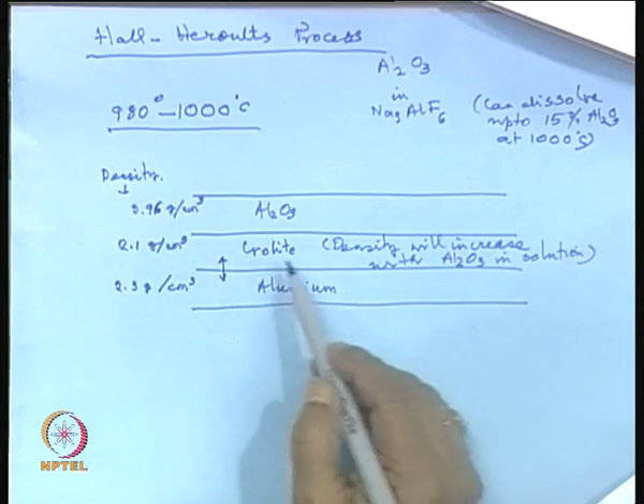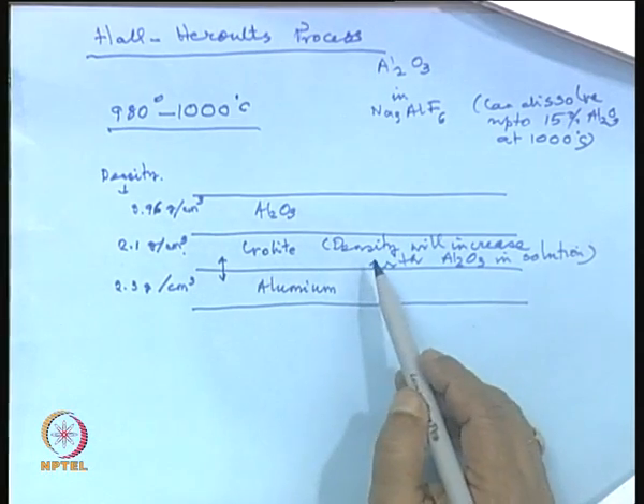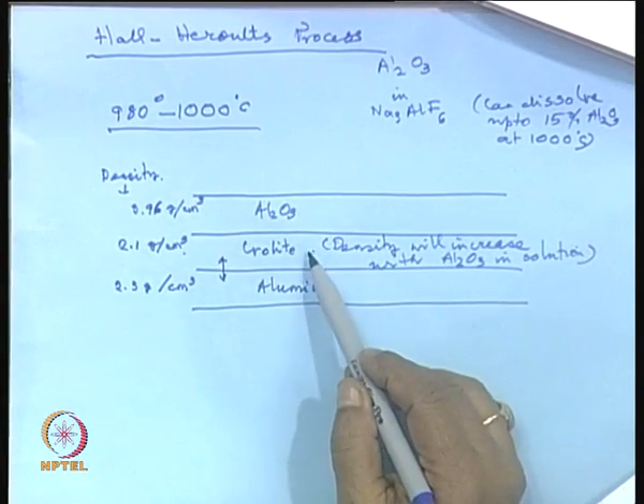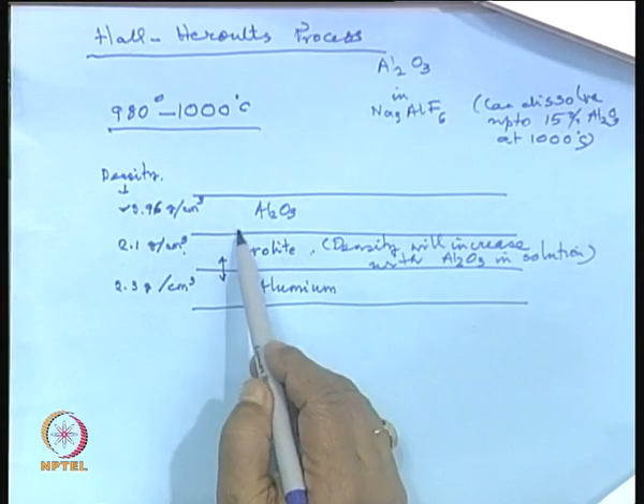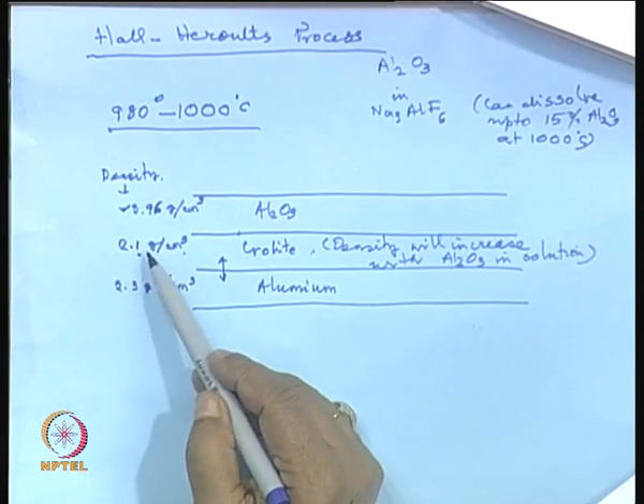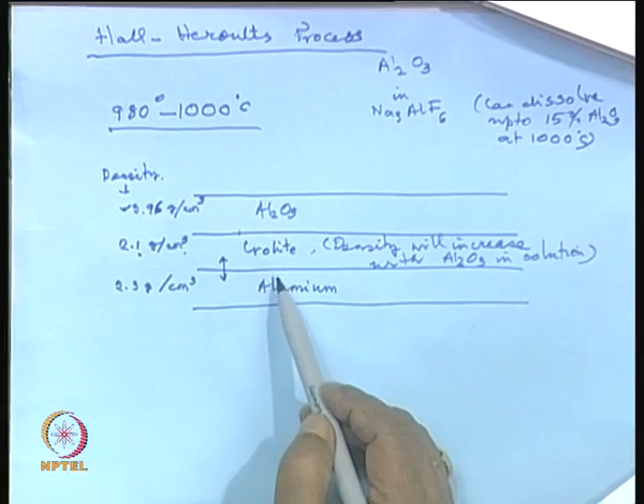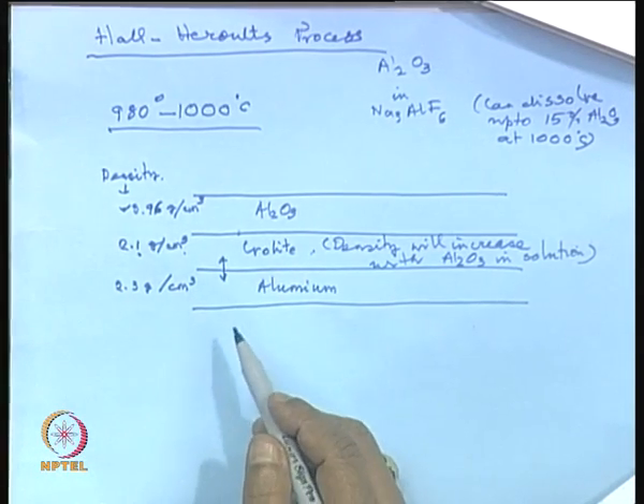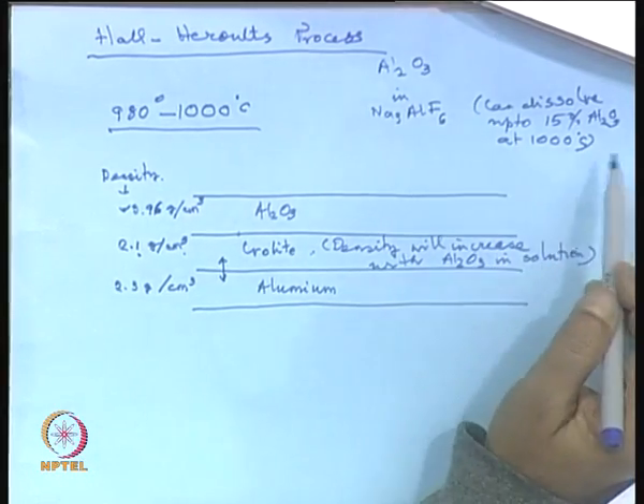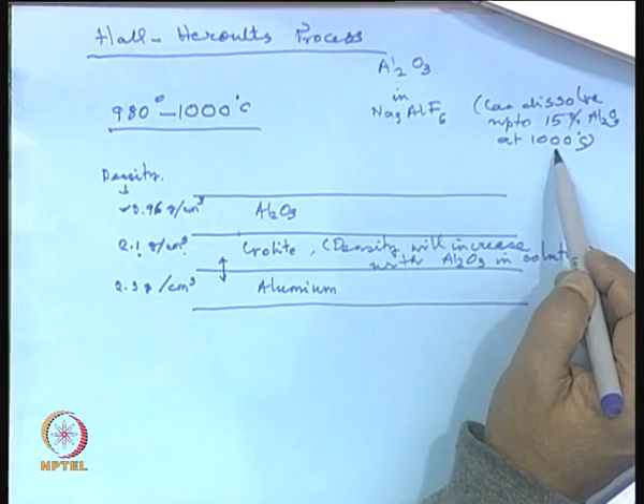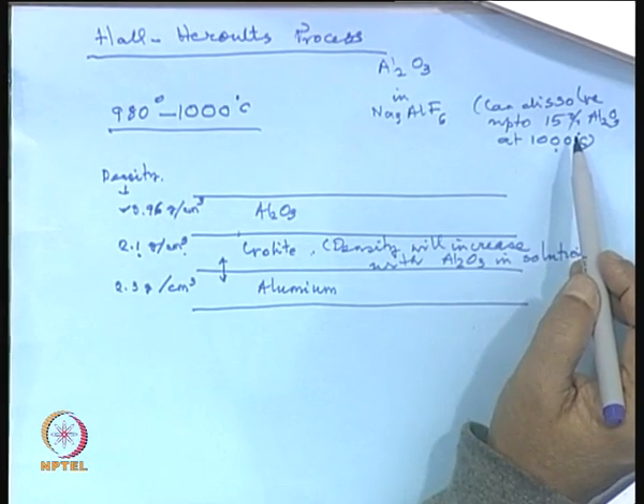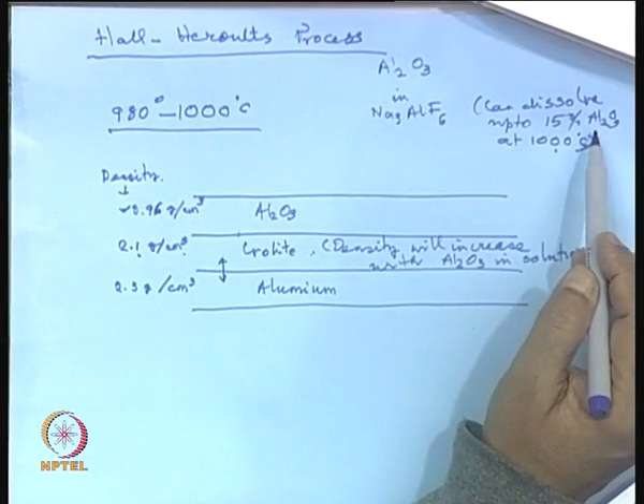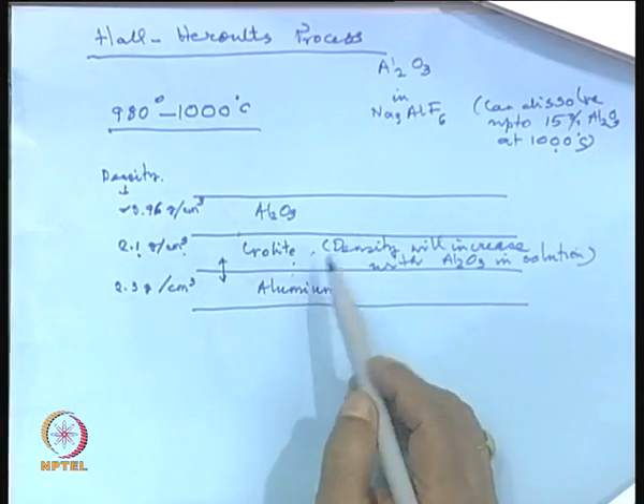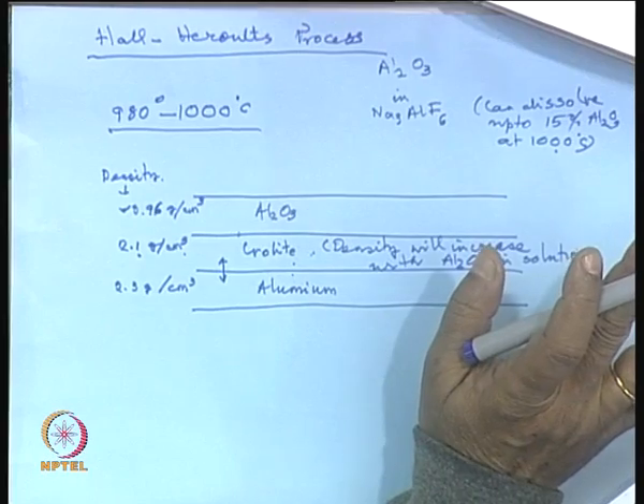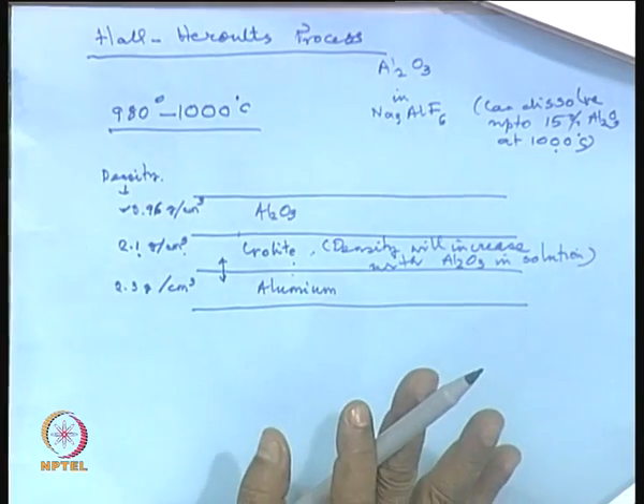Now, the real trick is here, that the density of cryolite will go up if more and more alumina goes into it, because alumina is of higher density. We do not want the density to become too high, then aluminum will not sink so effectively. Fortunately, we cannot dissolve too much alumina anyway, because there is a limit. At 1000 degrees we can dissolve only up to 15% alumina, but still nobody would like to go to that. We would like to maintain a density difference. So, one would operate at about 8% alumina only, not more than that. So, this is the situation.